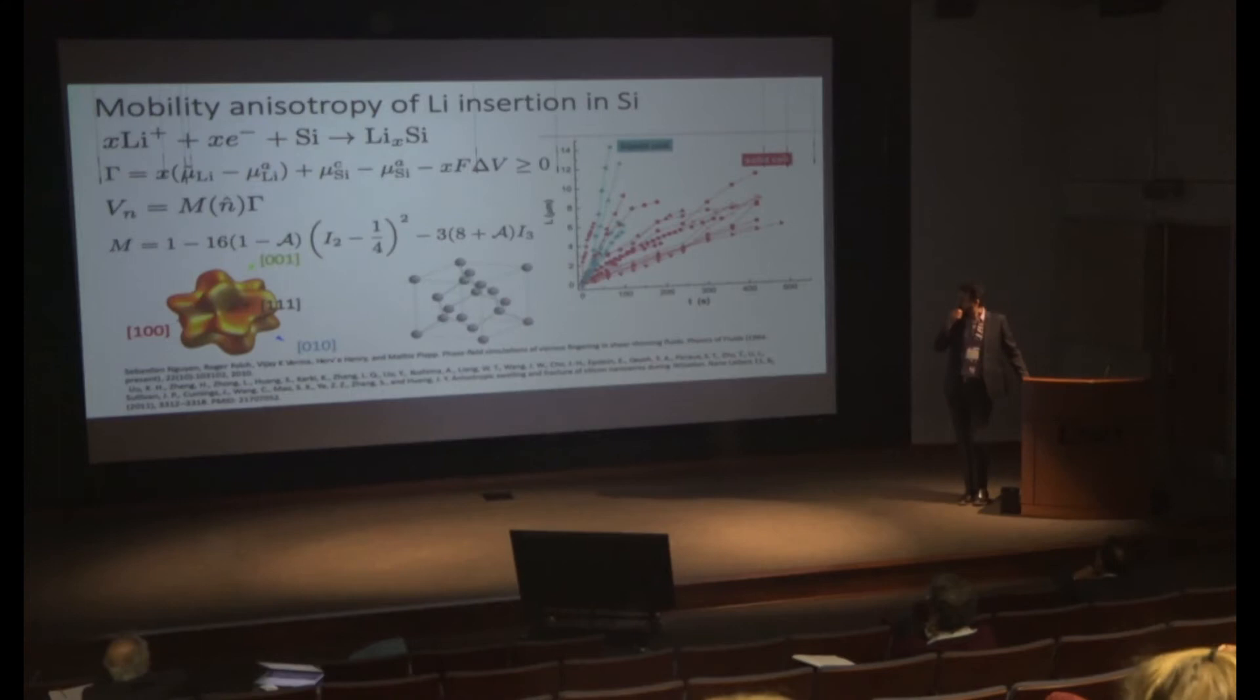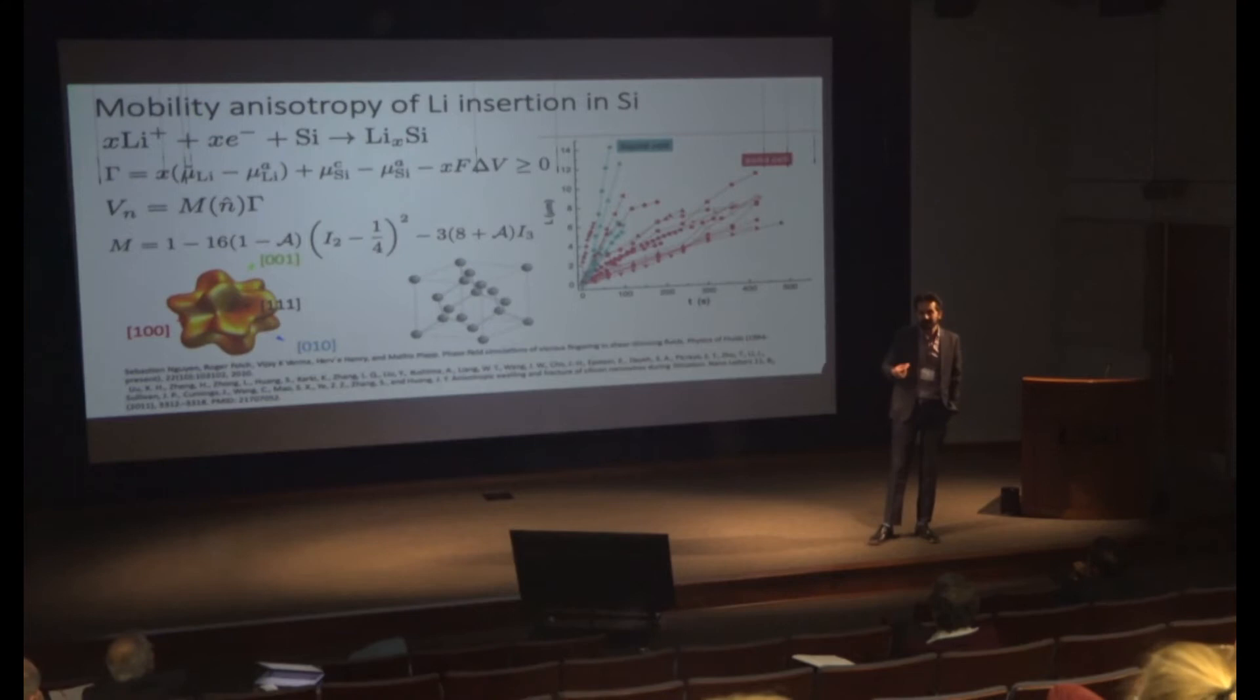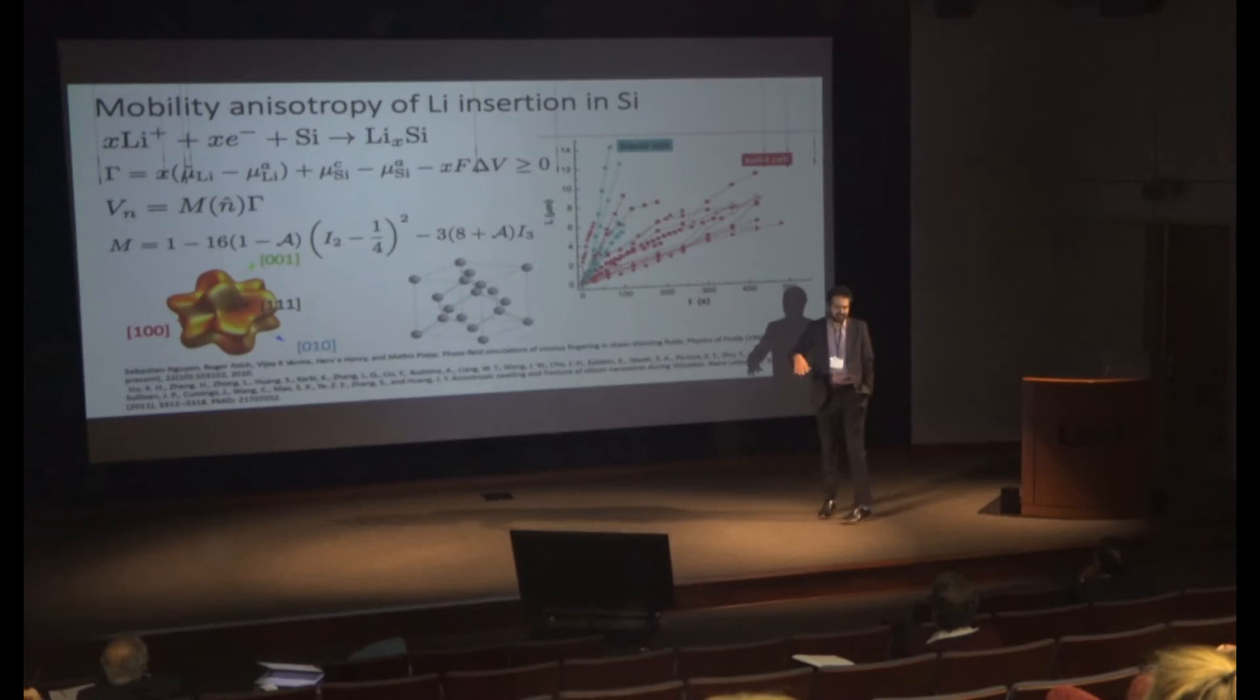How does the phase change work? When you look at this phase change, the lithium once it comes in, the phase change is slow but the diffusion of lithium in the lithium-rich phase is fast. On a fundamental level, I should have two equations—a diffusion equation and a phase equation.